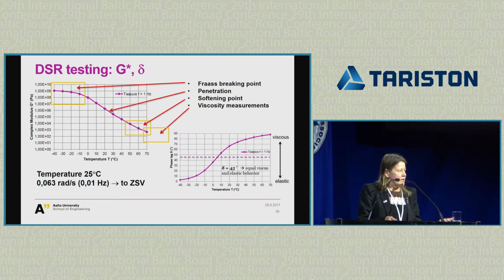loading times. And if you think about these two parameters, stiffness and the phase lag, it is very interesting in a sense that it tells how much the material flows relative to how much it doesn't flow. Of course, it stores and dissipates energy at the same time. The more I think of this phase lag and its importance, the more I think it is very important, because if the material has low phase lag, it means that it's more elastic. It doesn't really flow. And if it doesn't flow, how can it heal? So at high temperatures, if you get cracking, and at low temperatures, if you get cracking, if you can't heal the material, the cracks will propagate and grow.